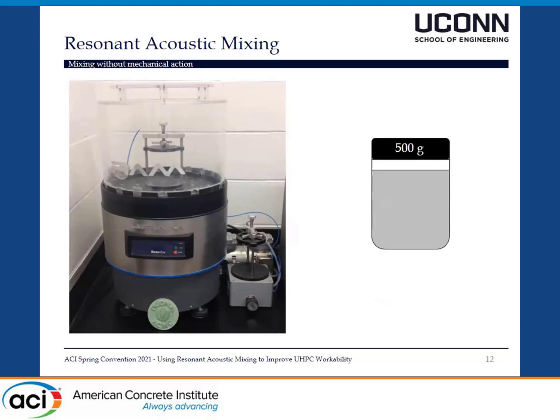And the basic principle of how it works is that you have some closed container. In this case, it's 500 grams, but in improved later versions, you can increase this amount since this is such a small container. And it's clamped down onto this platform that lies on several springs. And these springs oscillate back and forth. The spring motion induces a longitudinal acoustic pressure wave through the medium. And the amplitude of the wave is approximately 1.27 centimeters, or about a half an inch or less, for an acceleration of 100 times gravity. The gravitational acceleration constant is 9.81 meters per second squared.